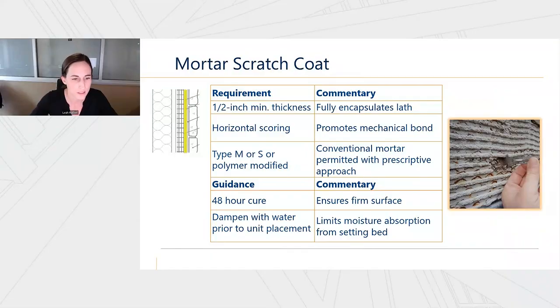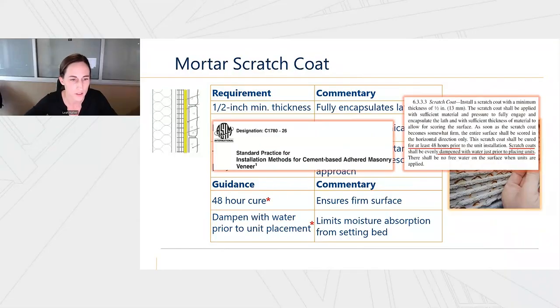Moving into some additional guidance regarding scratch coat, you can see there's a reference here to the ASTM C1780, and that recommends a 48-hour cure. That's intended to ensure a firm surface, and the purpose of that is to resist any force of pressing units into place that might unintentionally move the lath or reduce that thickness. So that's just a general recommendation there. And then along with that is dampening the surface with water prior to placement of the unit. Same thing, that eliminates potential for moisture absorption or kind of wicking the moisture out of the setting bed.